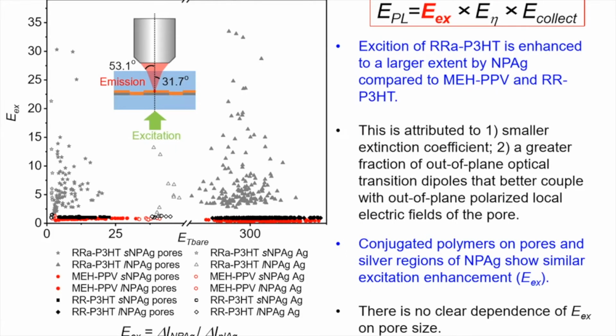In addition to the quantum efficiency enhancement, we also looked at the contributions to the photoluminescence enhancement from excitation enhancement and improvements in the collection of the emission to our detection system. So here is quite a busy plot, but here is plotted excitation enhancement versus the transmission enhancement of the bare metasurface compared to planar silver. Overall, the main message of this plot, it's a little bit difficult to judge, but you can see very obviously, at least for the regiorandom P3HT, that there is a strong excitation enhancement, whereas for the other two polymers, the MEHPPV and the regioregular P3HT, there's not much of an excitation enhancement.